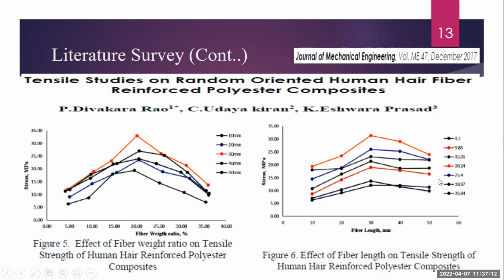And if I talk about the fiber length, you can see that a 30 millimeter fiber length gives us good strength compared to the other fiber lengths. They worked up to a 50 millimeter range of fiber length. It means we can conclude that chopped fiber gives a good result as compared to long length fibers.